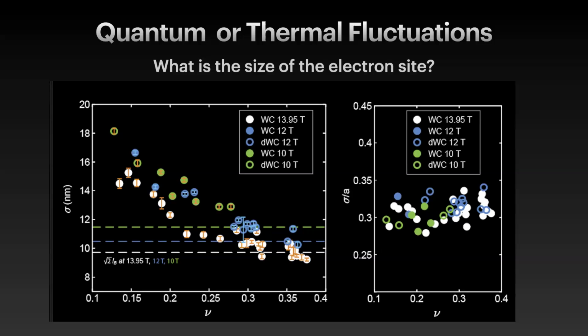You can kind of understand why sigma gets larger at low filling. Electrons have more space. There's nobody around. They will spread themselves out. As they go towards very dense lattices, they don't have much space. They repel one another. It's probably best to think about this as a phonon mode of some sort of an electron lattice. And in fact, those dashed lines that you see are if you assume the zero-point motion of this Wigner crystal lattice with this magnetic length of LB.